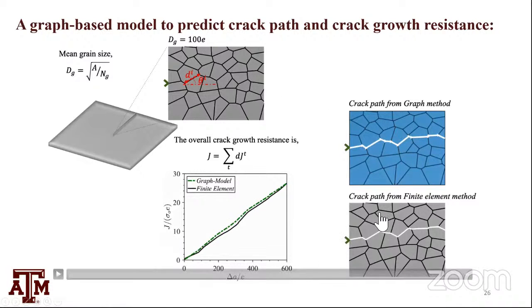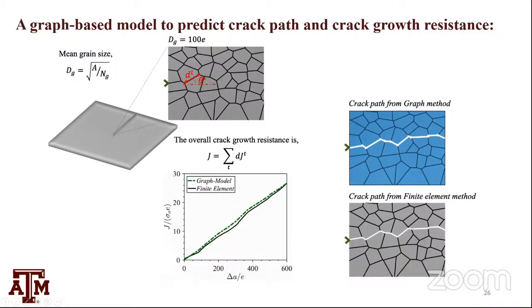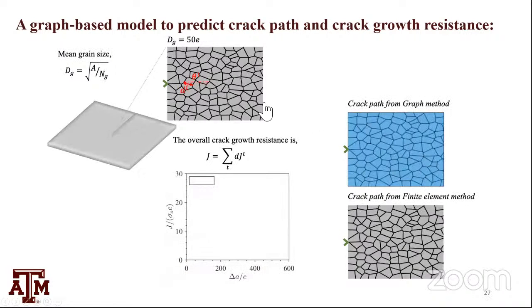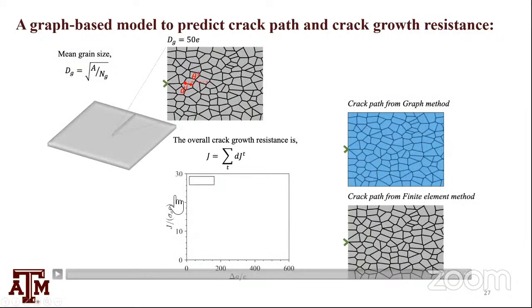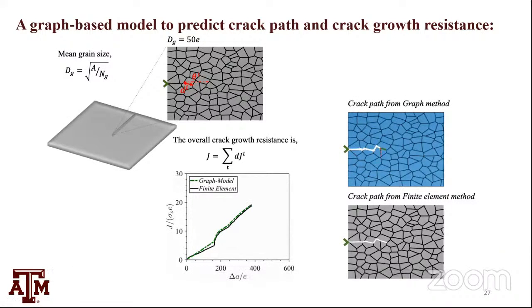We did this for a rather large grain size. We did it for a smaller grain size, half the grain size that I showed in the movie before. Again, every time I reach a triple junction, I have to pick this or that, and it does pretty good. In grain boundaries, we most often end up picking what we want. Again, these are 2D calculations, 2D predictions. We're not at 3D yet, neither is Google Maps.